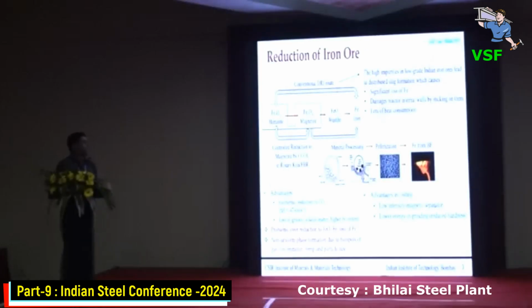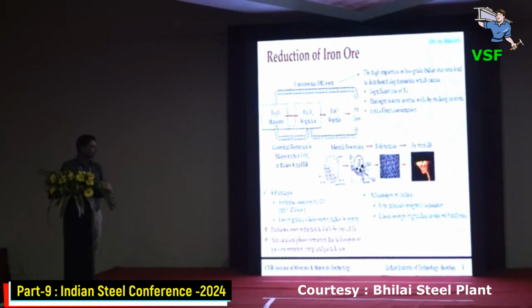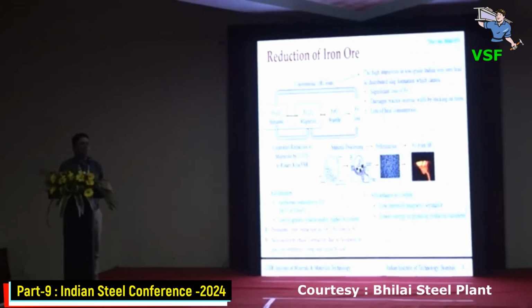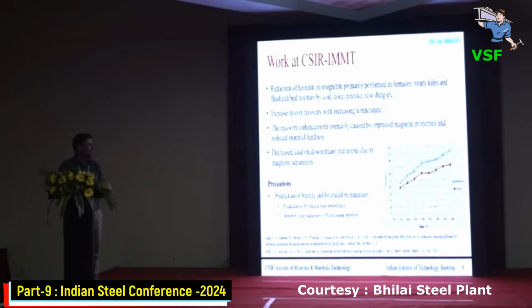So what we are suggesting and trying is that we do a controlled reduction up to magnetite, so that the magnetic susceptibility of this material is increased significantly, and we can do the magnetic separation. So the load on downstream operations is also low, and due to magnetic properties, and if we are doing the high temperature operation, porosity is created, because of which grinding is also easy and takes less energy. There are many advantages of this process. The process is of low cost, and the most important thing is that after adopting this kind of process, we are able to deal with the low grade ores, which is a main problem nowadays.